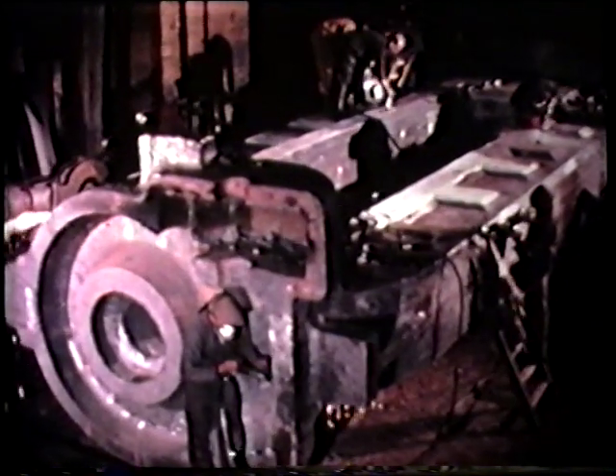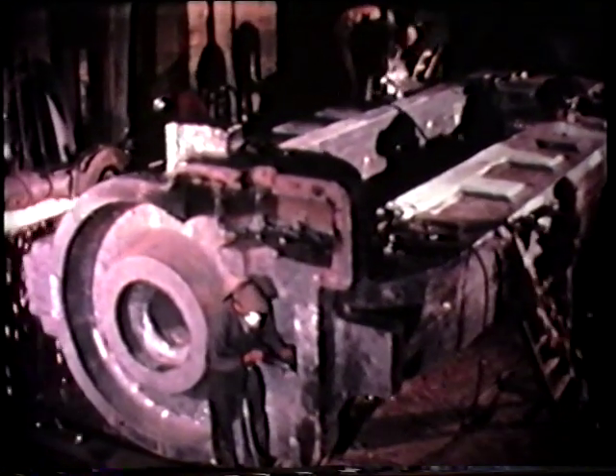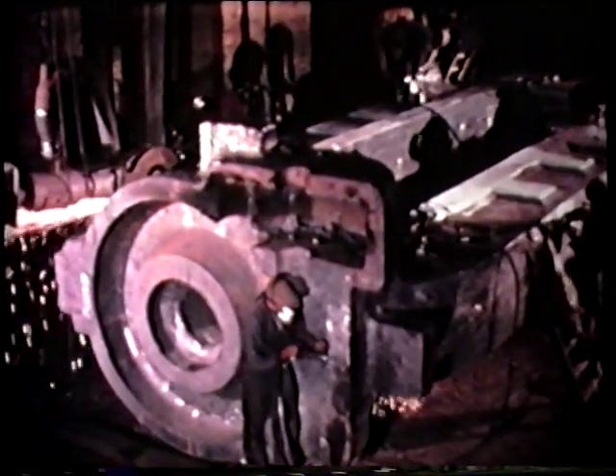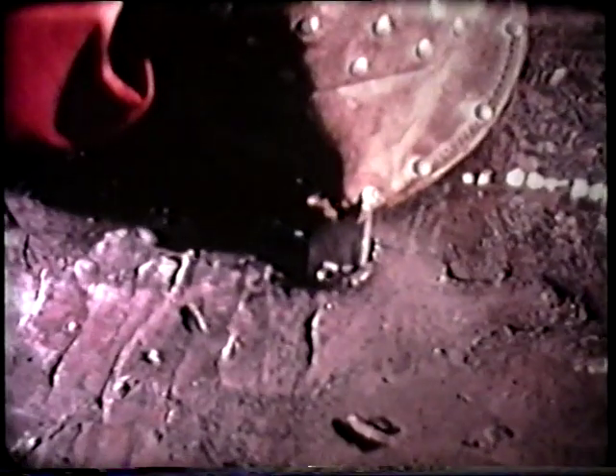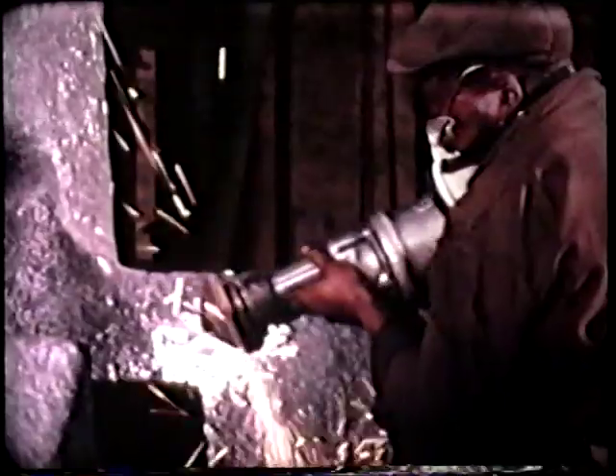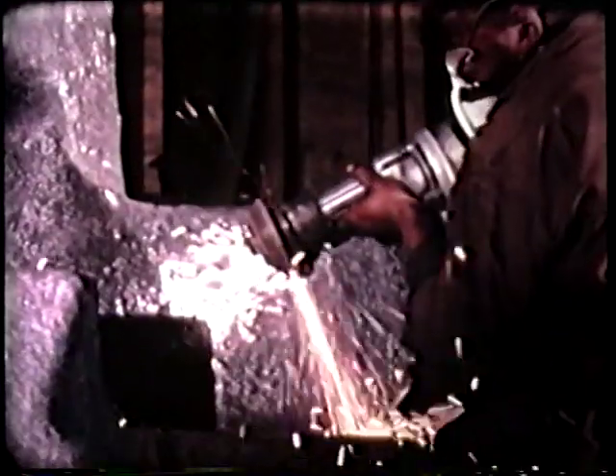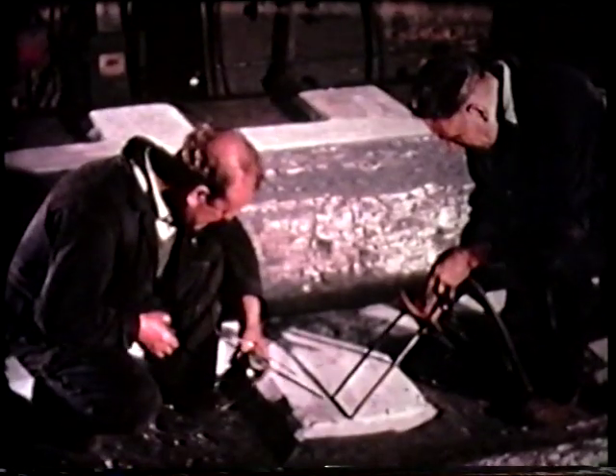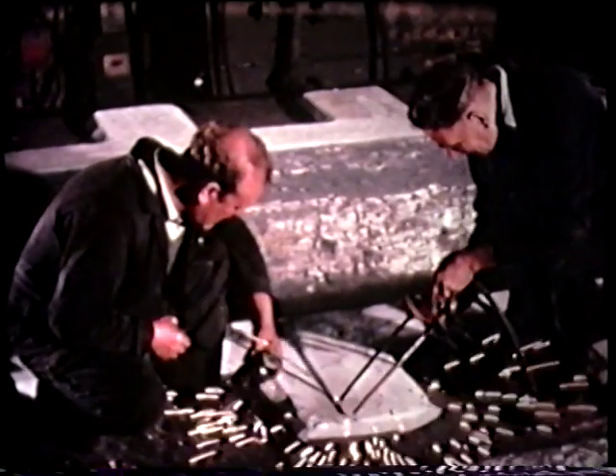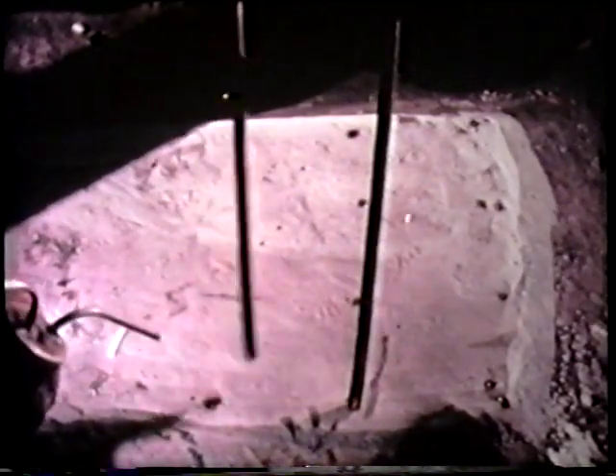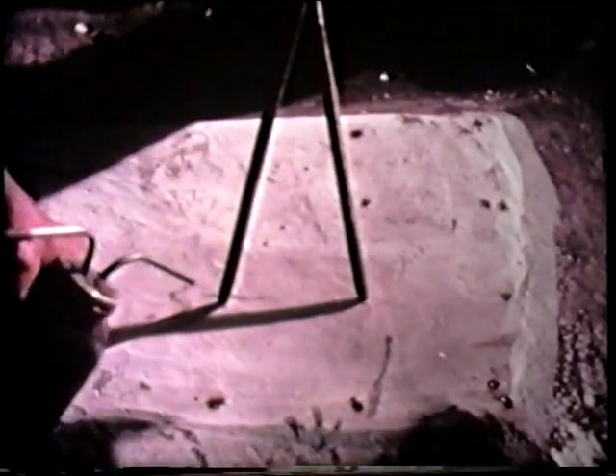The housing is now in the fettling shop and almost finished. The last of the surface irregularities are chipped away with pneumatic hammers, and the surface is smoothed by grinding. A crack detection test is carried out on all areas which will be machined. Iron powder is blown between the probes and will show as a thin black line if there's a crack.